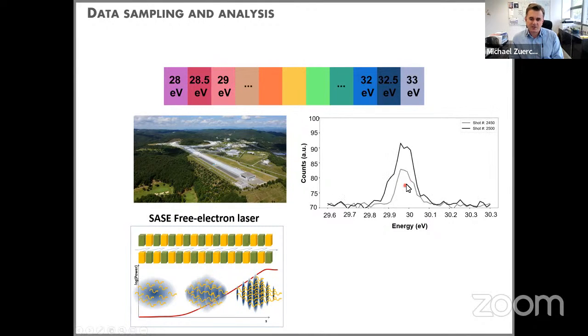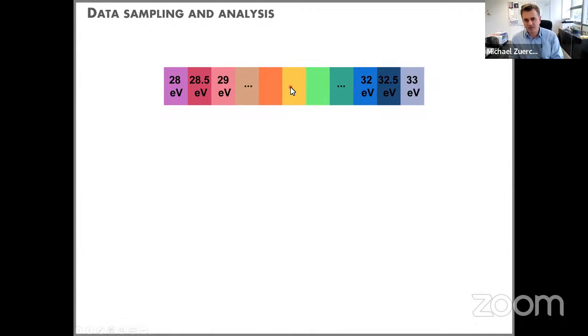If you want to do a spectroscopy experiment, what you would typically do is, by changing the undulator period, the undulator spacing, tune the central photon energy to different energies. You typically request that from the facility operators, and they will change the central photon energy, and then you illuminate your sample with a number of shots.